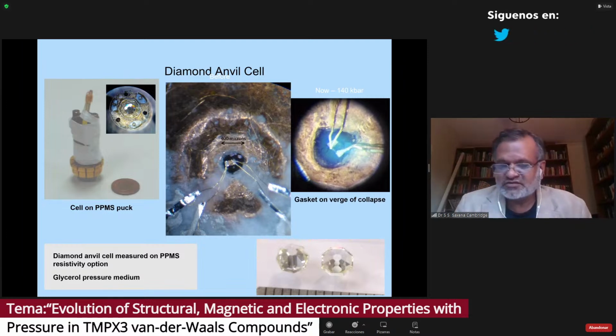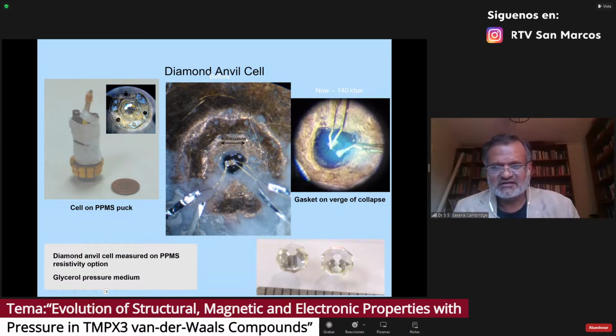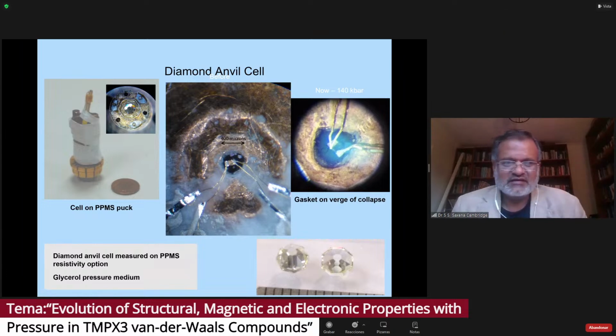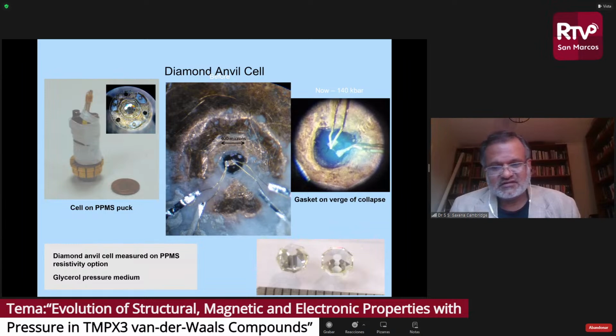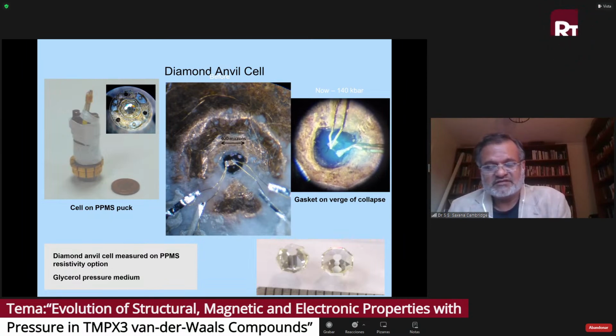which are often very, very difficult to do if you are dealing with an air sensitive material. You have to go to small scales. Any material, if it's sensitive to the environment, will die. Here we have to sit there and build these pressure cells so we can actually do these measurements. And these materials serve that purpose very well. So this is diamond anvil cell work.